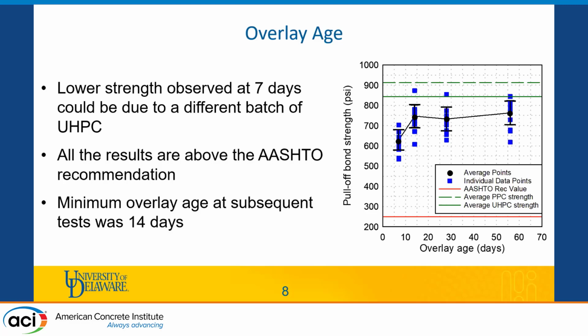And that was from a different batch of UHPC than the other experiments, and that probably was the cause here. So a good thing we see is that all the experiments of the overlay age are way above the AASHTO requirement, and that's a good thing. And we could adopt any of these ages.